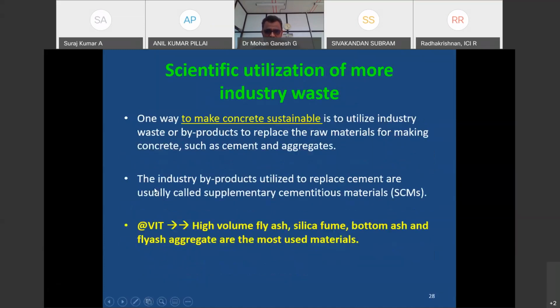Now, for making good sustainable concrete, we have to utilize industry waste or byproducts to replace the raw materials for making concrete. The raw material may be either cement, fine aggregate, or coarse aggregate. With that, we can easily make sustainable concrete. Here, if we replace the material with cement, it is called supplementary cementitious materials, simply SCMs, also called binder materials. At VIT, we have done high volume fly ash concrete, with up to 60% replaced with fly ash.